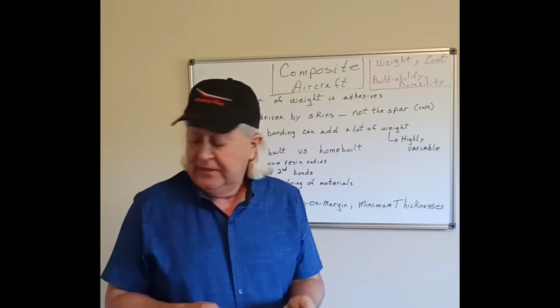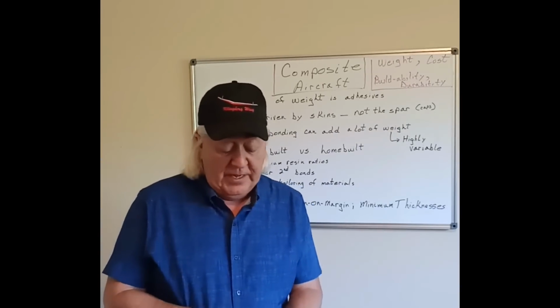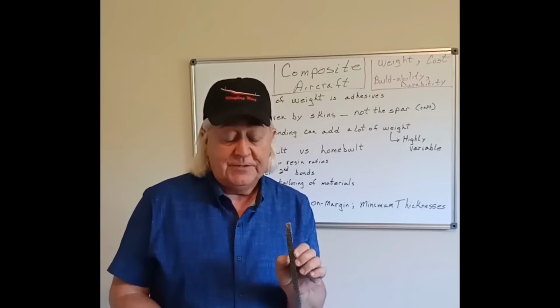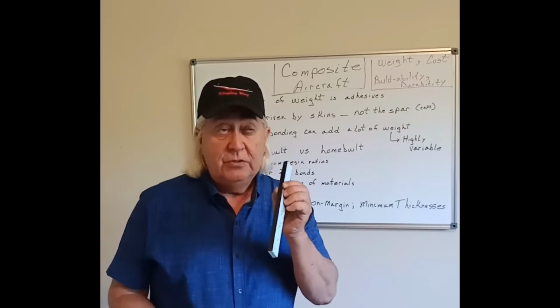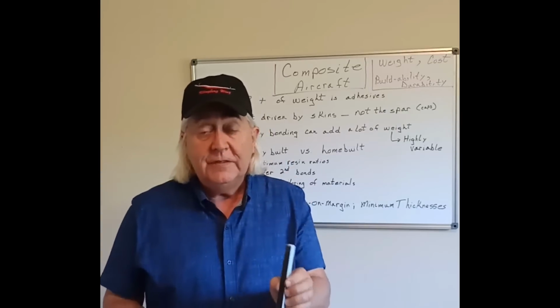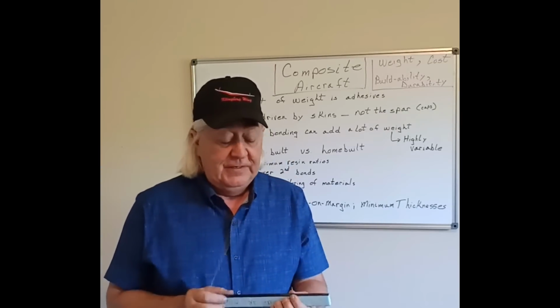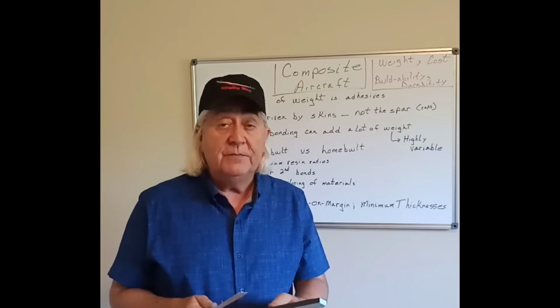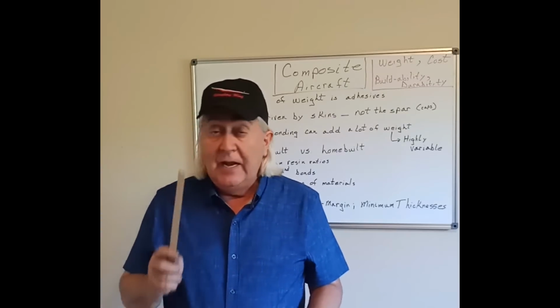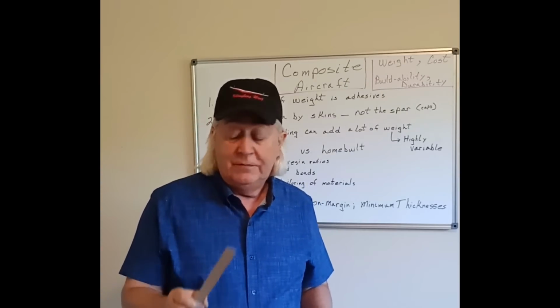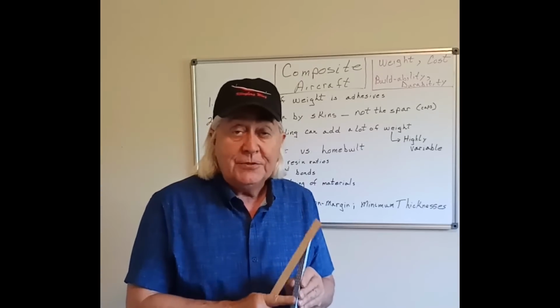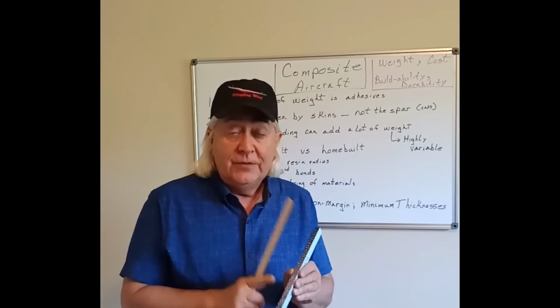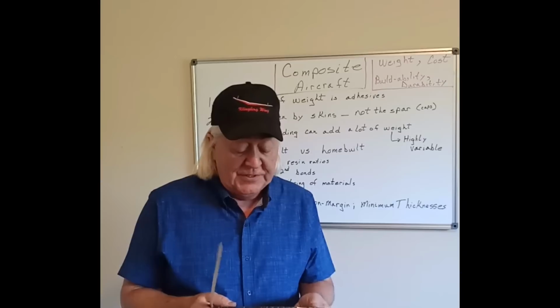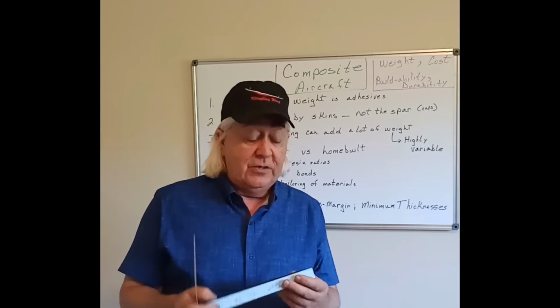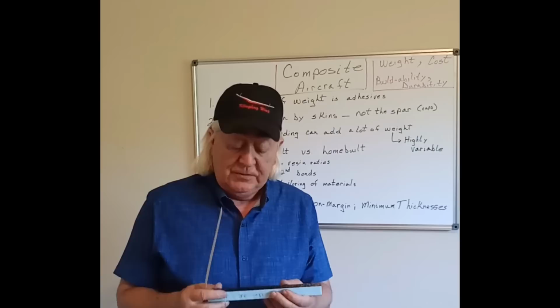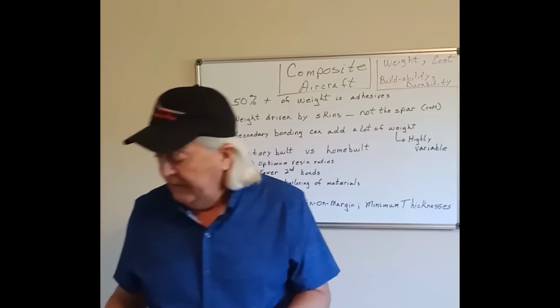So I made up some samples. I don't have them here, but some had wider caps and some narrower caps like this. And this was strong enough, not as strong as this, but strong enough and much less adhesive involved in attaching them and less weight in the cap strip itself. So the conclusion was, don't make the cap strips any wider than the rib material. So how wide does the rib material have to be? Well, you might be able to go down to 1/4 inch. These are 1/2 inch. You probably might be able to go down to 1/4 inch or 3/8, something like that.